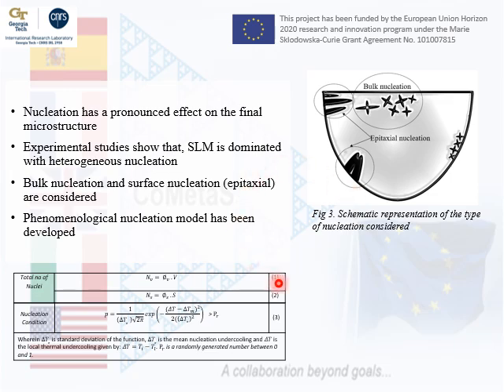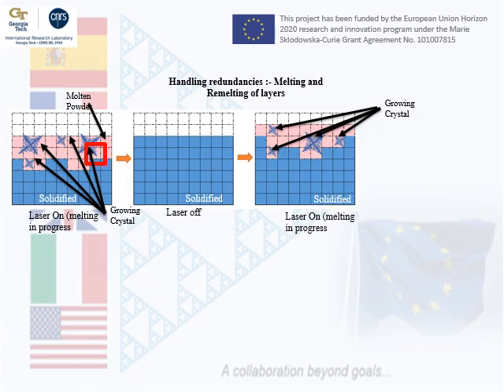And then the microstructure, when the dominating mechanism is epitaxial nucleation, is normally going to end up as a columnar microstructure. Because we're considering a stochastic process, we also need to consider the nucleation number. This is the number of nuclei that we observe per unit volume in the melt pool. And for nucleation, we have to consider a probability of nucleation. This probability depends on the temperature gradient, so the larger the temperature difference between the current temperature and the melting point, the more likely it is for a nucleation event to happen. And once we have these grains nucleating, the difference of the temperature of a cell with respect to the melting point is also going to cause the growth of the crystal.